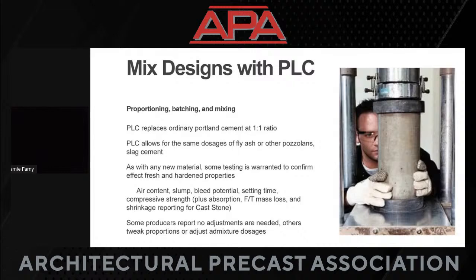As I mentioned under the standard slide, you can still use the same dosages of fly ash or other pozzolans, of slag cement, of silica fume with a PLC. They work really well together. But I will say, anytime you change a material, and you probably have experience with this if you're a producer, it's a good idea to understand how that material will affect your fresh and hardened concrete properties. What are the effects on that? So things like air content and slump, bleeding potential. Remember, these are very finely ground cements now. The bleeding is probably going to be impacted somewhat because you have a lot more fines that hold things together, hold the water in that mix better.